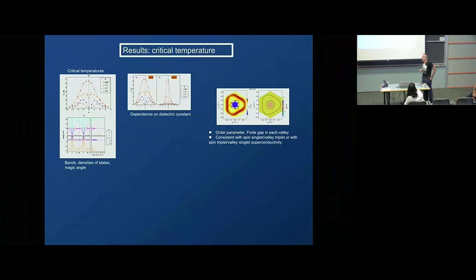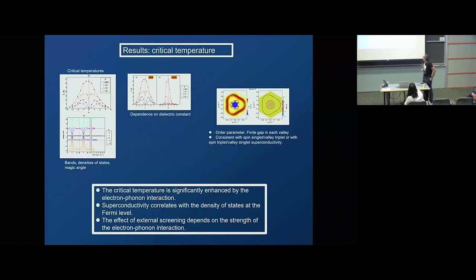Let me stress that you shouldn't trust too much a single calculation of a critical temperature. I'm a theorist and I know it well. So we were looking for trends rather than particular values. The fact that we get 2 or 3 Kelvin is good for us, but we didn't give a lot of relevance to it. But this kind of mechanism gives sizable, let me put it that way, in the right range of parameters, critical temperature.